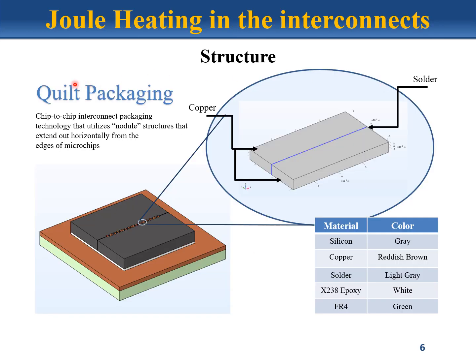So here we talk about the quilt packaging structure used in the simulation. As we can see here, there are two silicon substrates with nodules in between them. If we take a closer look here, we can see that there are nodules of various widths along the edge of the two silicon substrates. Taking a deeper look at them, we can see that one of those nodules is 200 micrometers wide.